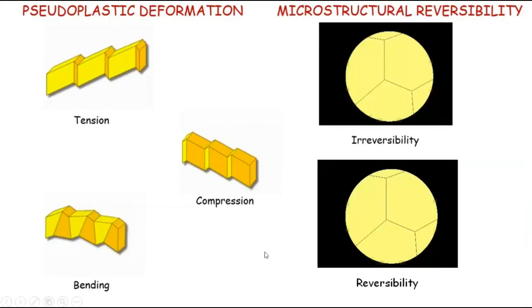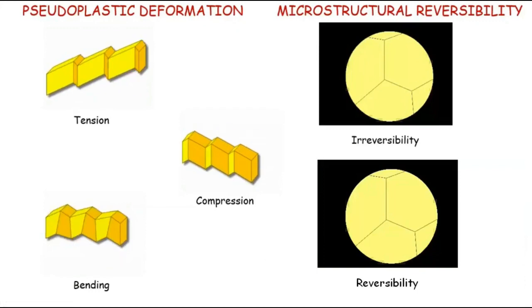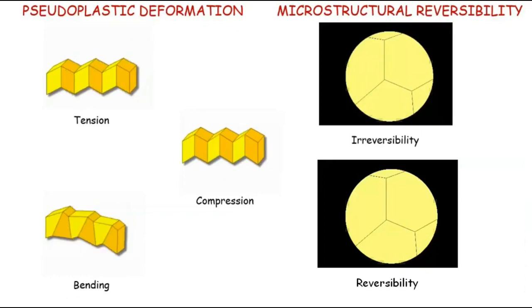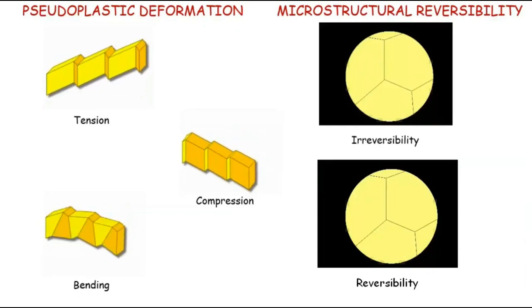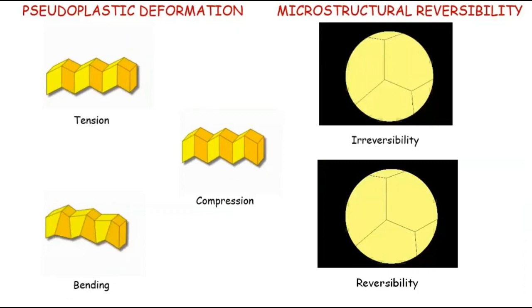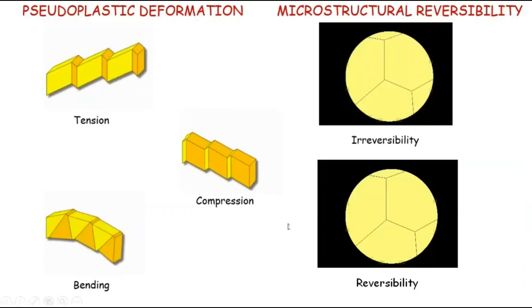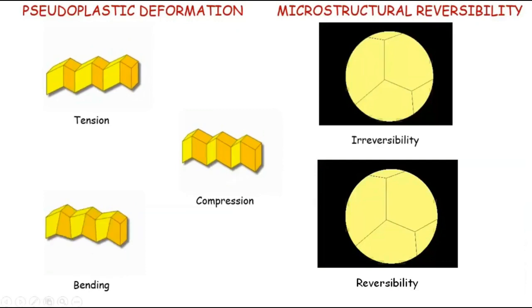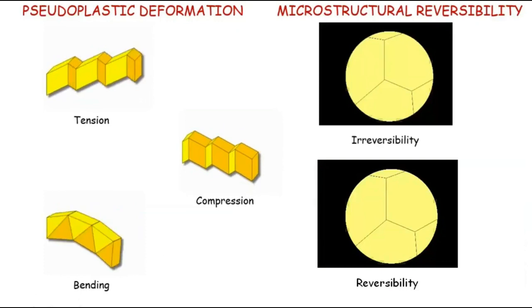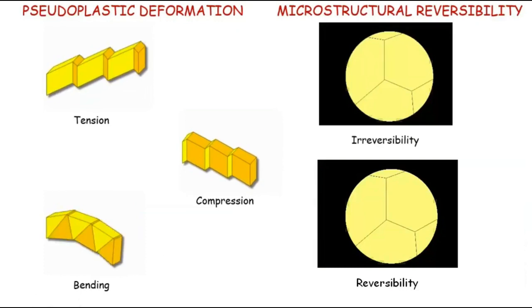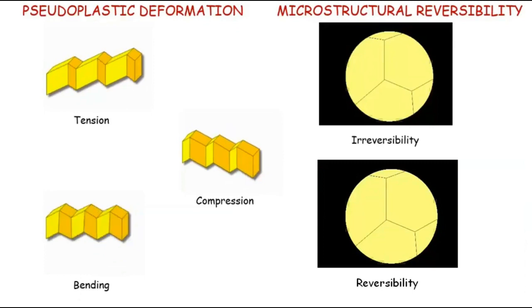If I would do the same thing in compression, it would be the orange one that would grow at the expense of the yellow, and then one can guess what will happen during bending. All in all, it says that in pseudoplastic deformation, you can get a macroscopic shape change essentially by rearrangement of the variants, and it happens because you are able to move these variants. And what has happened in the movement of this glissile interface is that you're twinning. So there's a twinning transformation, if you want to call it that, that happens when the glissile interface moves, and in this way, it rearranges the entire microstructure, and you see a macroscopic change.